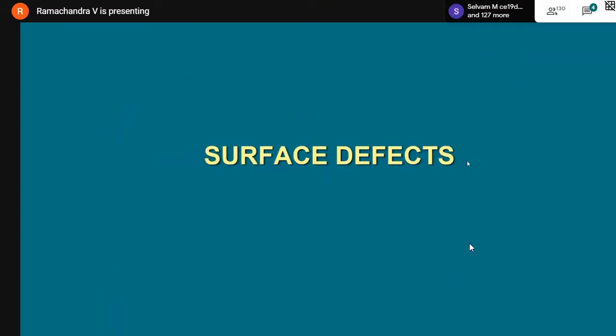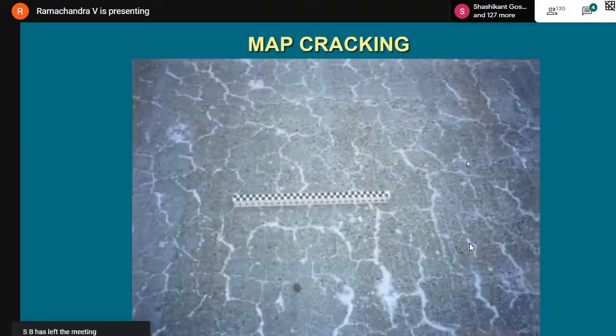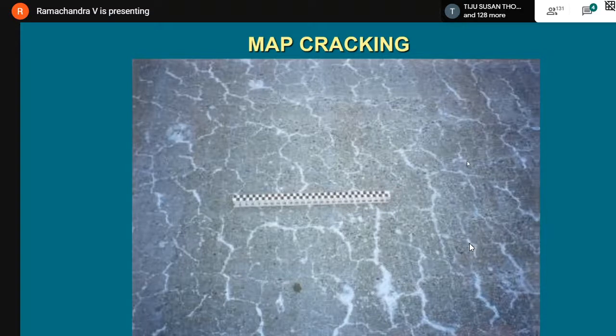Let us go to surface defects now. The surface defects are not structural, they are functional. For example, map cracking or plastic shrinkage cracks. This is very common in concrete pavements. Why does it occur? It is because the water cement ratio is very low and admixtures are there. When the concrete panel is subjected to either high wind or high day temperature, the surface water of the concrete evaporates, and that leaves these cracks. These cracks are very random, map cracks. There is no regular spacing of fissures. That is why it happens.